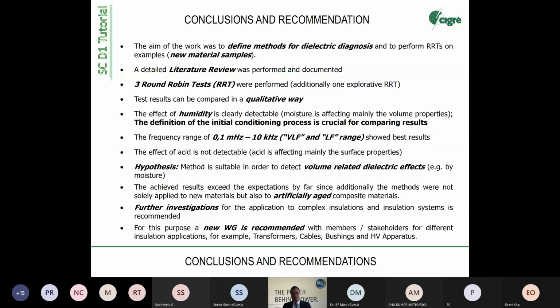The effect of humidity is clearly detectable. The definition of the initial conditions is crucial for comparing the results. It's also clear afterwards; at the beginning, it was not clear. Frequency range: we should work from 0.1 millihertz, not deeper, because otherwise it's time consuming and we do not learn anymore, because the scatter in this low-frequency area is going up, and it's not necessary. We can see the effect already at 0.1 millihertz. We also do not have to go further than 10 kilohertz, because the effects are disappearing; the ions are very heavy, so they do not move much in high electrical fields. They just make a little bit of movement, but do not contribute to the response anymore.